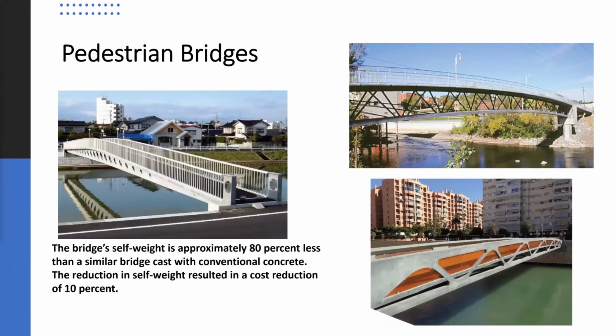Next, we'll be discussing applications for UHPC. So the first application we have is pedestrian bridges. As you can see from the pictures, the bridges are lighter and thinner compared to conventional cast concrete bridges. Besides having a very high compressive strength value, which exceeds 22,000 PSI, current research shows that UHPC is believed to have a high tensile strength value that may reach 1,700 PSI. With that, the bridge's self-weight is approximately 80% less than a similar bridge cast with conventional concrete. The reduction in self-weight resulted in a cost reduction of 10%.